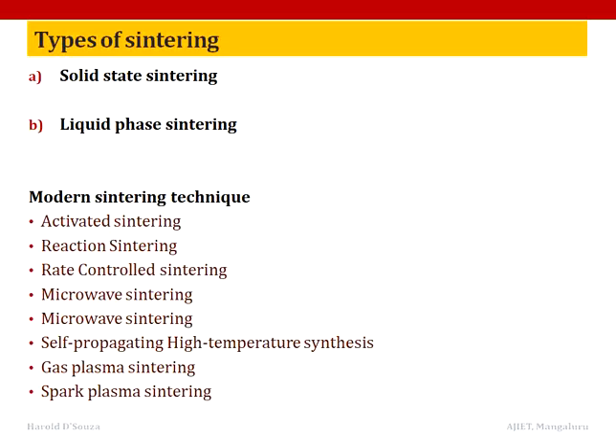Now, by diffusing over the tungsten particles, nickel accumulates at the neck of the particles from where the nickel penetrates to grain boundaries. Now, this presence of nickel at the grain boundaries greatly increases the grain boundary self diffusion of the tungsten. Thus, the segregation of the additive at the interparticle boundary creates a short circuit diffusion path for the rapid diffusion of the base metal, resulting in the enhanced densification. To promote activated sintering, any additive must form a low melting phase during sintering and also must segregate at the grain boundaries. The additive must also have a very high solubility for the base metal so as to promote rapid diffusion of the base metal through the additive phase.